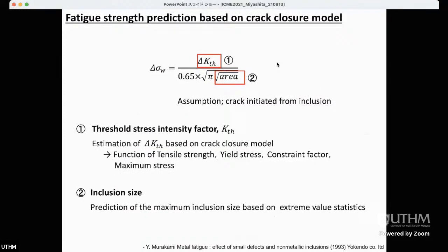And next, we try to predict fatigue strength based on the fracture mechanics approach. So we start from this equation. We want to calculate fatigue strength, and in this case we need a value of delta K threshold and crack size, meaning inclusion size, because we assume that the crack always initiated from inclusion. And in order to predict this inclusion size, we predict that based on extreme value statistics proposed by Professor Murakami in Kyushu University.